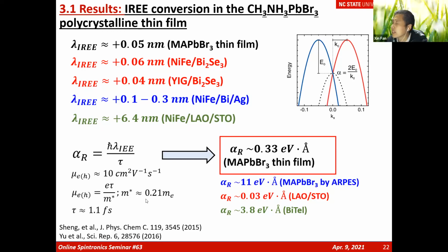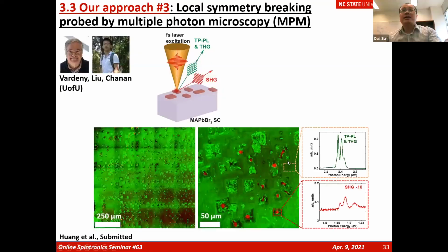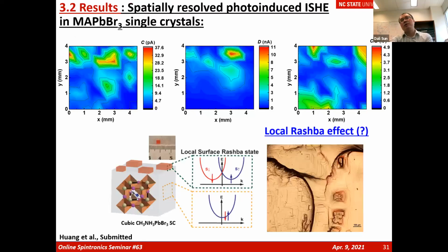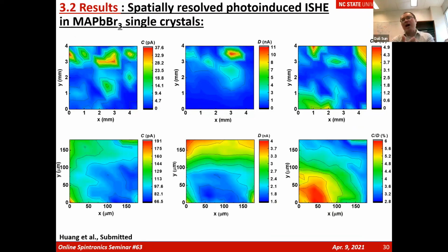I missed that figure. Is it micron size? Yeah, the spot is in the 10 micron size. 10 micron size. So you cannot really do spin pumping, even though you know where the location is. You cannot pattern your sample to do spin pumping, can you? No, we can't. So that's why we had to use the second harmonic microscope. And even with photo-induced ISHE, we have a resolution of somehow like 5 microns. You see the red spot on the right corner, and it really demonstrated that the spot contributed to the CPG responses. I see.